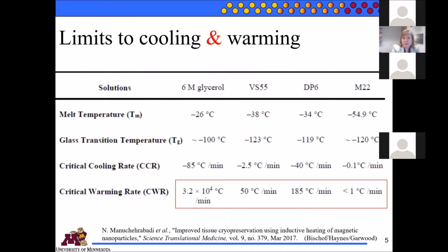So let's look at what they use for cryopreservation agents. These are basically biocompatible antifreeze. They're not so biocompatible. So the method to freeze is that you would increase the concentration of the cryopreservation agent as you're cooling. That's actually how they're able to get a very good viable freezing of organs and tissues. The question is, once you get that high concentration, it's no longer very biocompatible. These are the different cryopreservation agents, they call them cocktails because they're mixtures of things like glycerol.